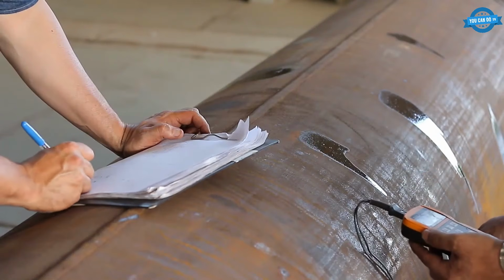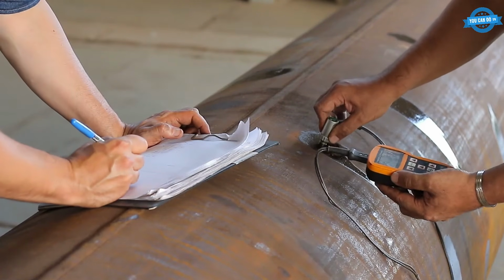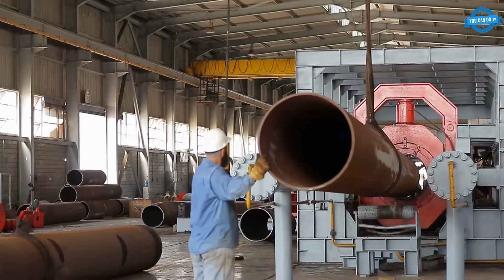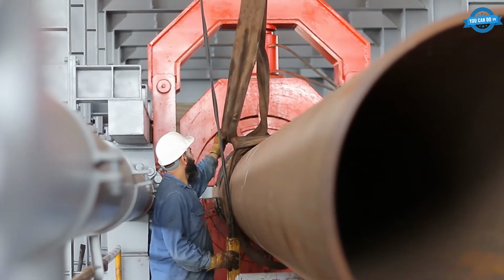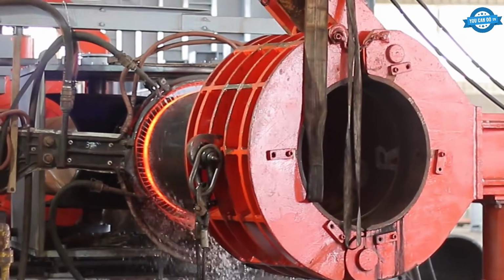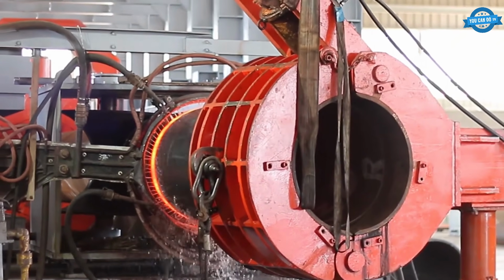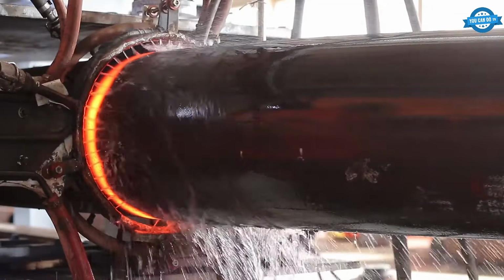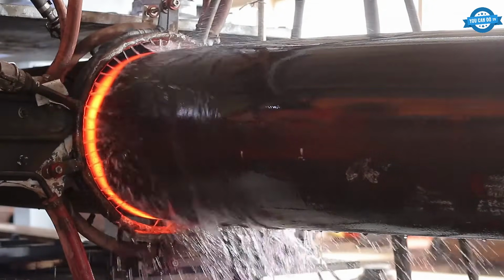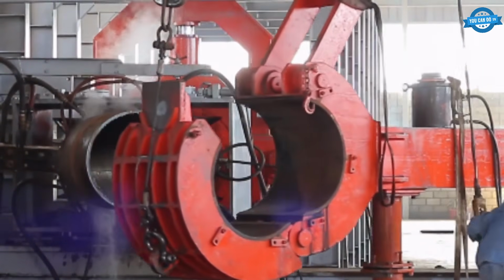Hot bending starts with the mother pipe arriving for inspection. The pipe loads into an induction bending machine, where localized induction heating glows a narrow band cherry red. Only that band bends. The rest of the pipe stays cool and stiff. The bend forms along the specified radius.